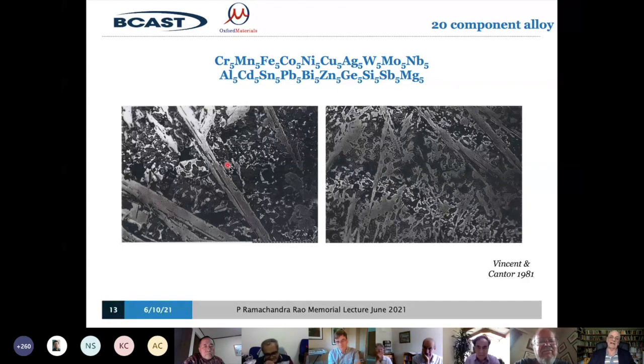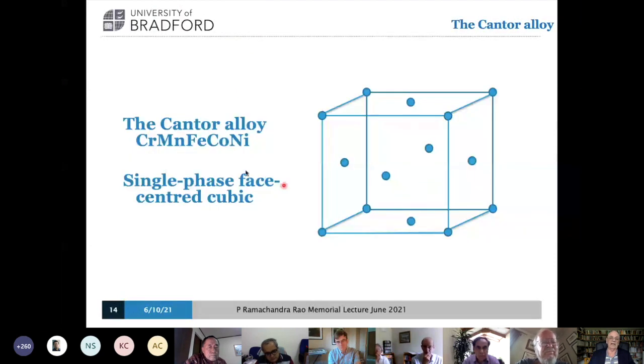But we then found something very, very interesting. This region here, these black regions, are what is now known as the Cantor alloy, the original Cantor alloy, the first Cantor alloy. The first Cantor alloy consists of chromium, manganese, iron, cobalt, nickel, five components in equal proportions, 20% of each: chromium, manganese, iron, cobalt, and nickel. And amazingly, nobody would have predicted it. I'll say why in a second. It turned out to be single phase, face-centered cubic. Nobody would have predicted that.